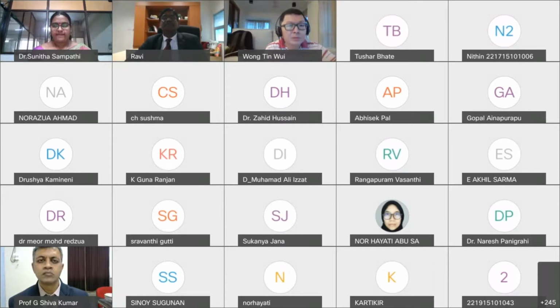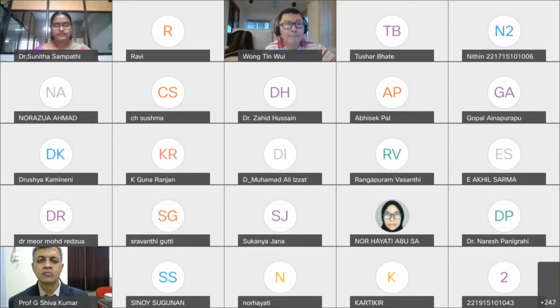But when I go through your stability slide, you mentioned that by increasing the time, the size was increasing. Based on your experimental findings and your experience, what could be the reason for this increase in size? It seems a significant increase within 15 days only. Could you comment on that?